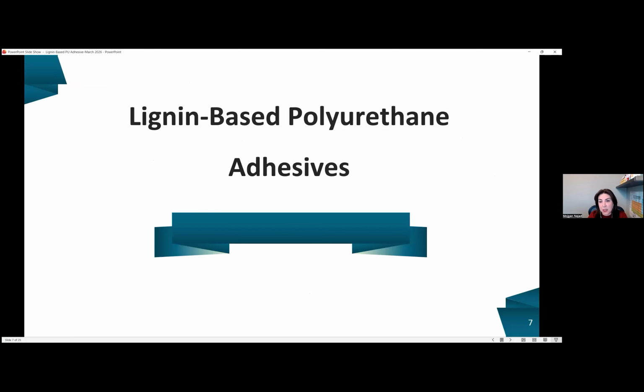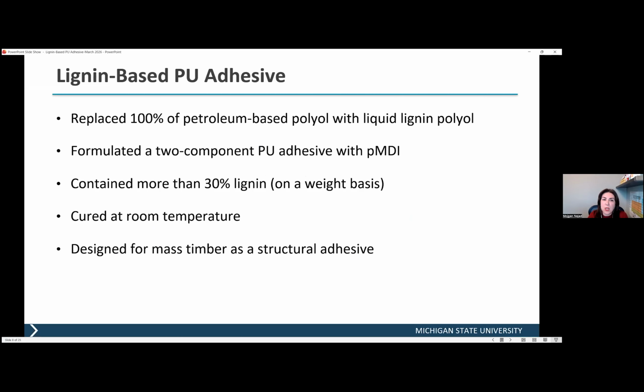Now I'm going to talk about the lignin-based polyurethane adhesives that we produce at MSU and are scaling up through our new startup. The lignin-based polyurethane adhesives that we developed replace 100% of the petroleum-based polyol, which is one of the main components of polyurethane adhesives, with our patented technology, liquid lignin polyol. Because it's in liquid shape, it is much easier to use in a manufacturing facility and mix with polymeric MDI as a second component to make these adhesives.